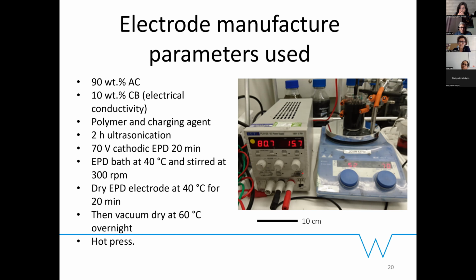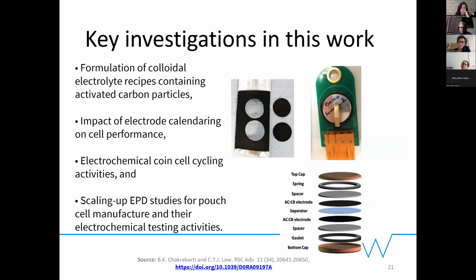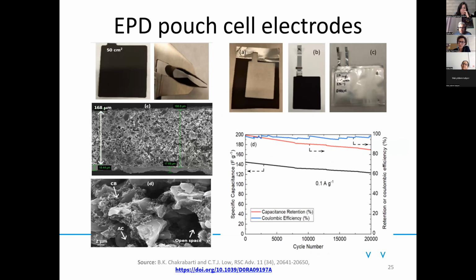So in some ways we are fortunate that we managed to get a thick electrode and good performance, but we need to do more reproducibility studies to make sure that it can be something that we can recommend to the industries in the future. The thickness is an important parameter for industry, I believe. Yes, they look for thicker coatings for high power systems, right? Exactly, and also for long cycle lives as well. First we did 20,000 cycles in this case, but I think they can go up to even longer, like 50,000 and sometimes 100,000.